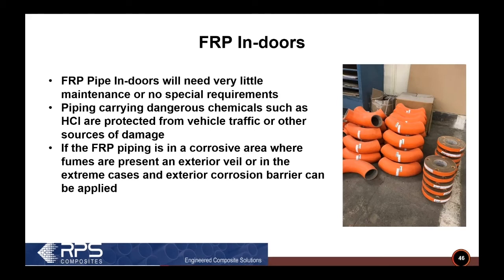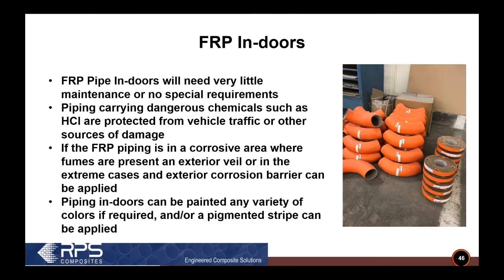If you had a really nasty environment that the pipe was exposed to, or the pipe's actually down inside of a tank, you would need to apply a corrosion barrier to the outside of the pipe. One of the nice things too about insulating FRP pipe is you don't have to worry about moisture getting in between the insulation and the piping. It's not going to attack the FRP from the outside like it would in metallic piping. And of course, indoors, like you can see in the picture, you can pigment the pipe any style you want. You could put stripes on it and do pretty much whatever you'd like to do as far as coloring goes.